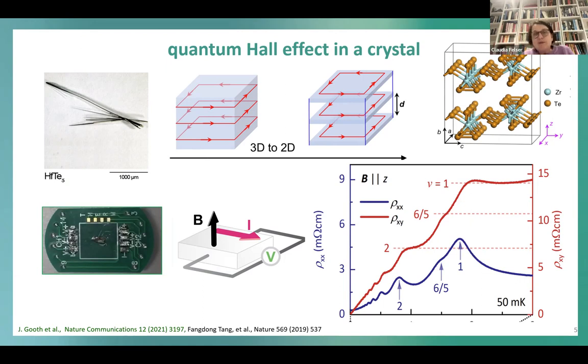So unfortunately, before 1984, nobody did this and nobody recognized this. Otherwise, maybe some chemists would have gotten the Nobel Prize, and they would have recognized these very nice plateaus, which you see in a simple single crystal of hafnium telluride, as you see here. And there was another Nobel Prize for the fractional quantum Hall effect. And even in the single crystal, if you go down to lower temperature, the plateaus you see already at 12 Kelvin or something, and these fractional values you see even at 50 millikelvin. So for me, it's really amazing.